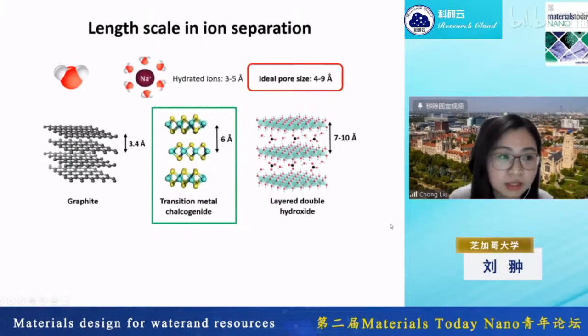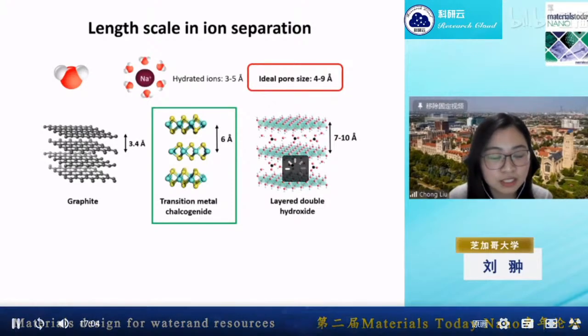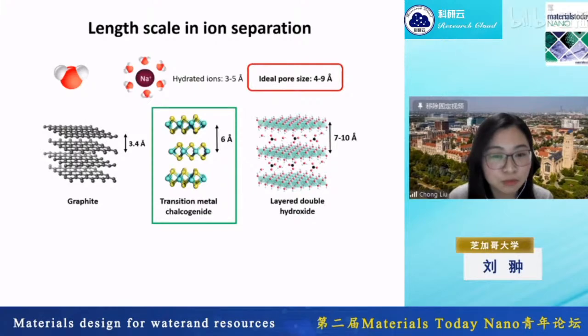So we are looking at the 2D material class. This class of material has a very interesting layer spacing that's exactly on the right scale. For example, in graphite, the carbon to carbon layer distance is 3.4 Angstrom. And for molybdenum sulfide, this class of transition metal dichalcogenide, the center moly to moly distance is 6 Angstrom. Even though they have a repeating unit of 6 Angstrom, the sulfur to sulfur distance is really tiny, meaning there's no free volume in this material. So in their bulk form, nothing can transport through this channel.